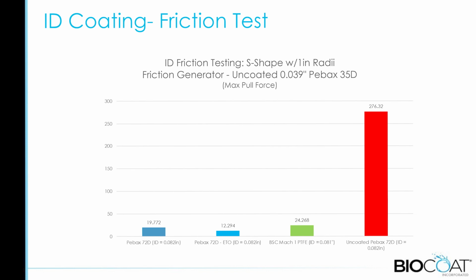And what we're finding is with our coated tubing of the same PEBAX, we're bringing it down to about that level of Teflon, or even in some cases a little below there. So 90 to 95% reduction in the friction from that uncoated material. And so getting it very comparable to the performance you're getting for Teflon. And in fact, I would say probably maybe a little bit better. Wow, interesting.